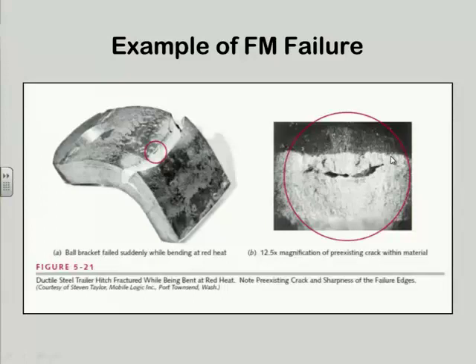Don't cut yourself. And look at the break surface, and you will see a little smiley there, which is a crack. And that piece of steel happened to have a crack in it. And when he grabbed that, put that pipe in the hole, and did this, he exceeded the fracture toughness threshold, and bing, it came apart. And you would never expect ductile steel to break like that, especially red hot. That's what killed the Liberty ships. They came apart as if they were brittle.